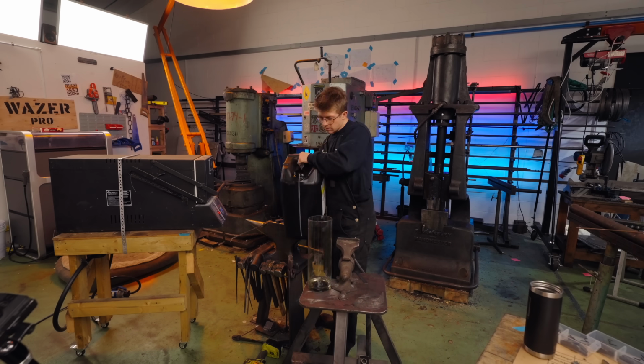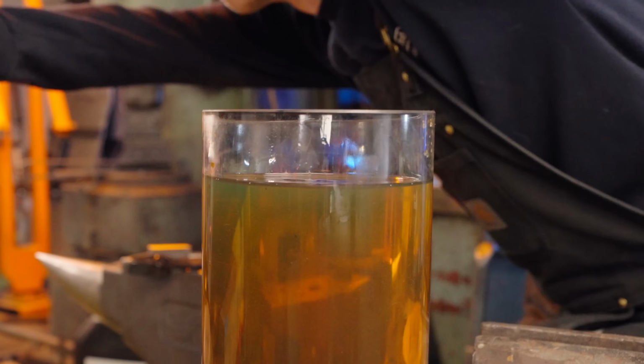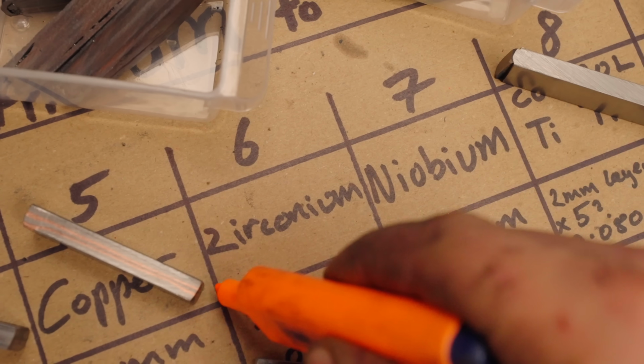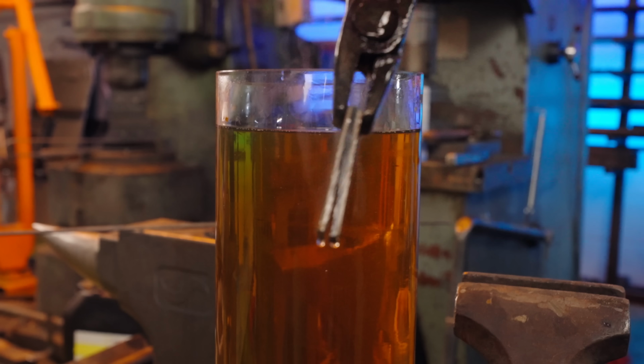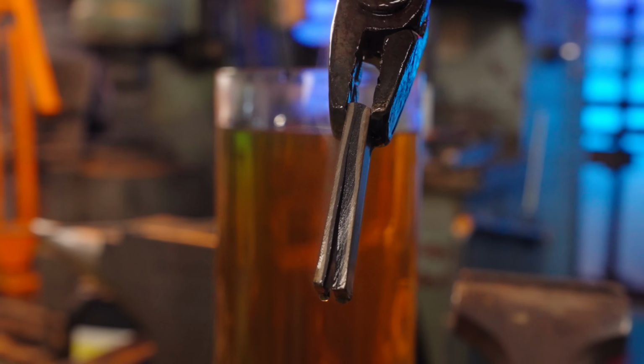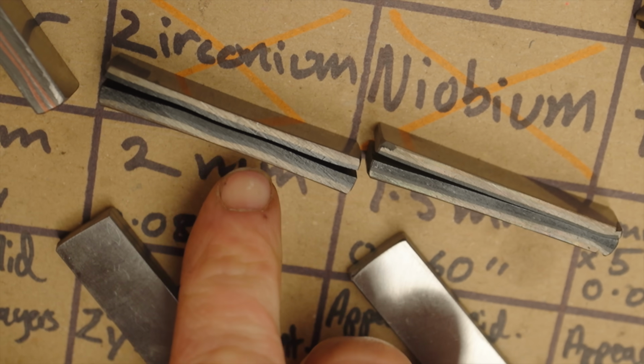Weird! For test number 2, we are going to harden and temper all our samples to see if they can withstand a heat treat, but it didn't take long for us to find a failure. Our zirconium and niobium samples both broke right after hardening. I was looking closer at the broken zirconium and niobium, and this is fascinating.